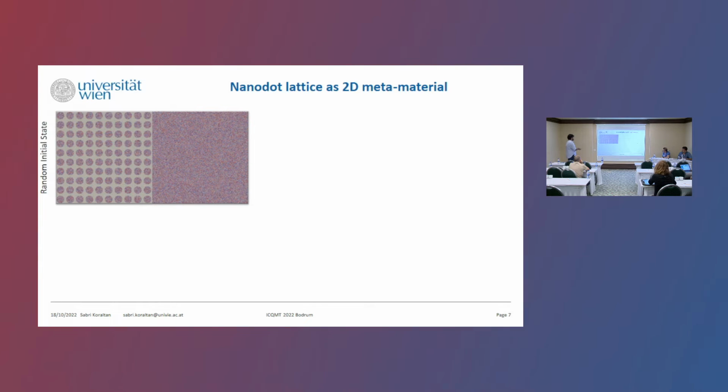In each cell, we start with a random magnetization state. And we first relax the structure, which means that we are solving the Landau-Lifshitz-Gilbert equation numerically. And we include energy terms from demagnetization, from uniaxial anisotropy, so PMA, and exchange. So we don't have any DMI in the system.